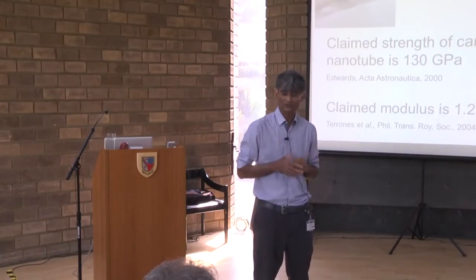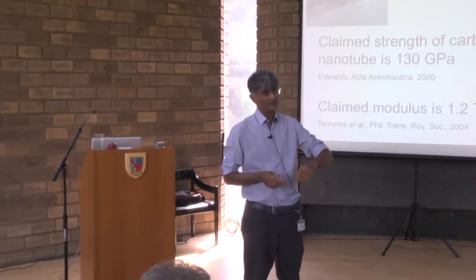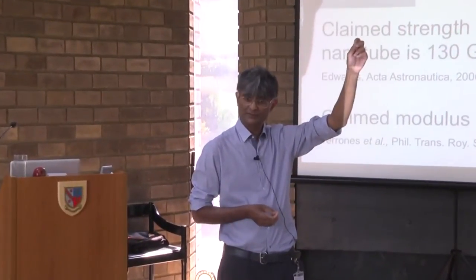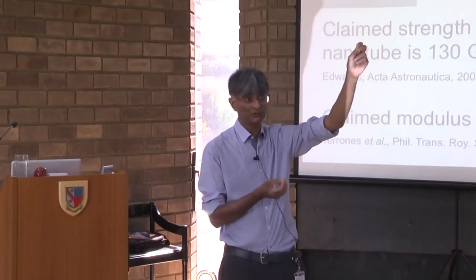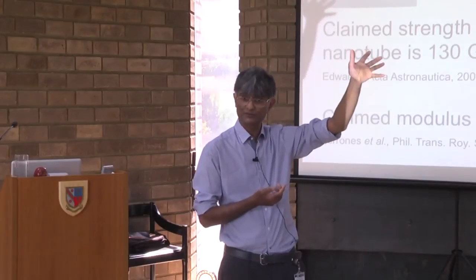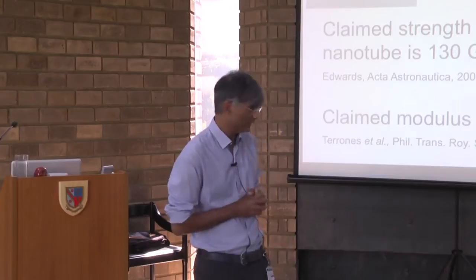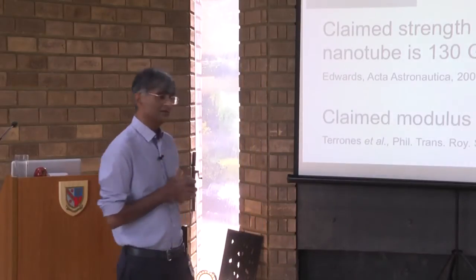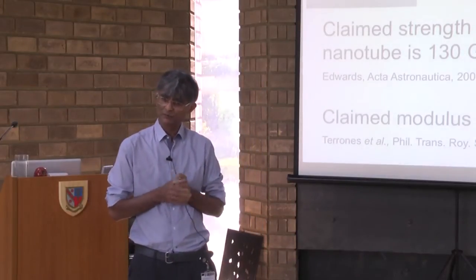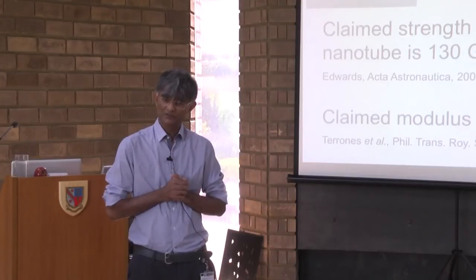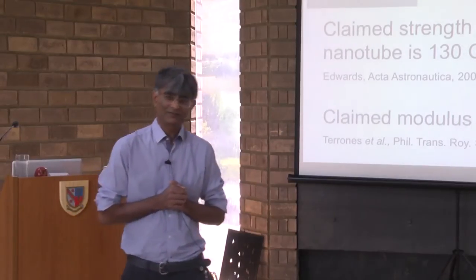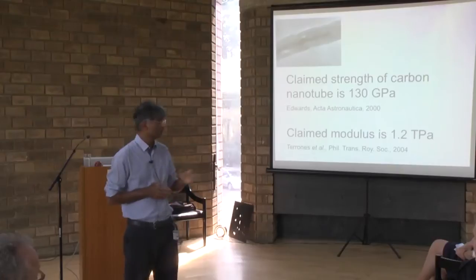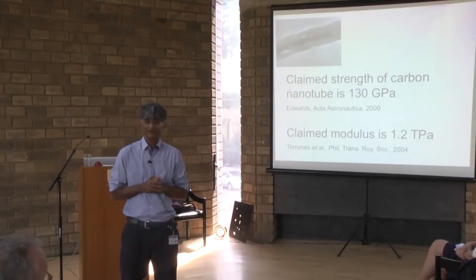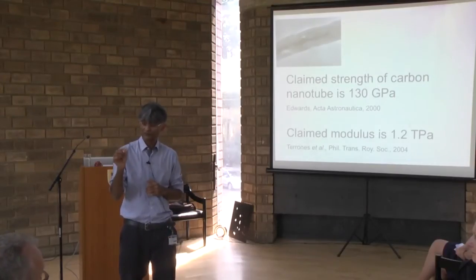Okay? This is an old Russian idea. The problem is that if you make a rope for the elevator, it's not able to support its own weight when you get to 120,000 kilometers, which is how long it would be. And I had a very hard time convincing him over a period of 4 hours that this is not a viable idea because these properties are only there for very, very small scales.